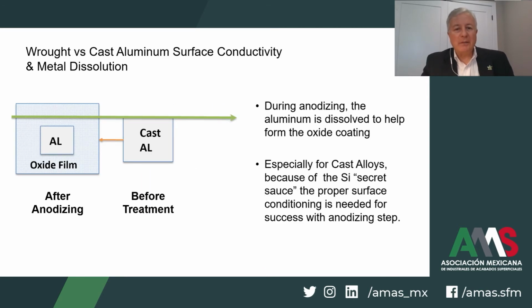Remember, in creating the anodized oxide layer, we're dissolving aluminum, and where we are having higher concentrations of silicon, the formation of the proper type of oxide layer is inhibited. So unless we do something different to overcome the high silicon concentrations in the surface, the anodizing will not be successful.